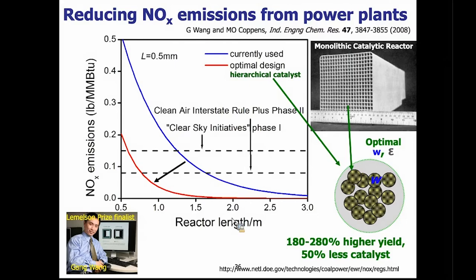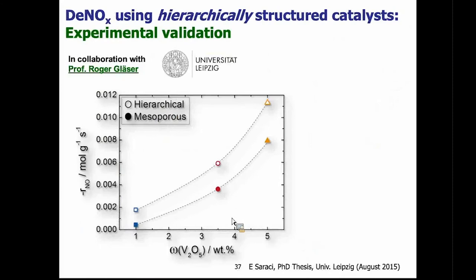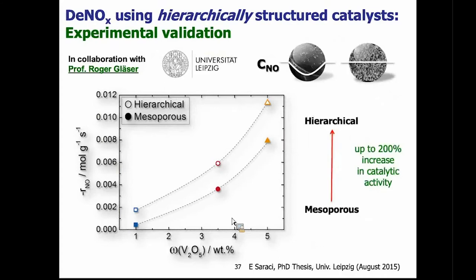The same catalyst, but using half the amount of material. So putting in more pores, but of the right sizes, can increase your overall yield. In this way, you have a much shorter monolith and you can convert your pollutants to not just pure nitrogen, and you can do this much more effectively.